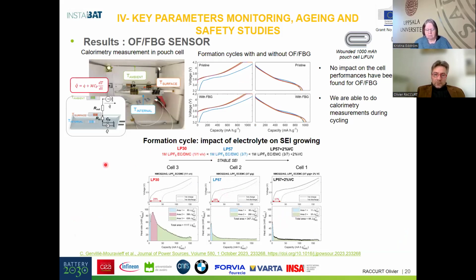With FBG, we can also access the thermal behavior of the cell. In this result, we are using FBG inside and outside the cell to monitor the temperature during the formation cycle. And we can study the impact of the electrolyte on the thermal behavior during the formation. By accessing this information, we can correlate it to the quality of the SEI. And you can take a look at the result in this publication from the CNRS Collège de France.